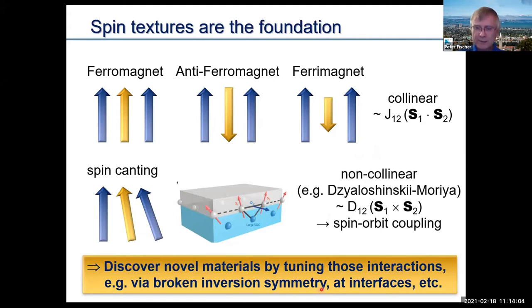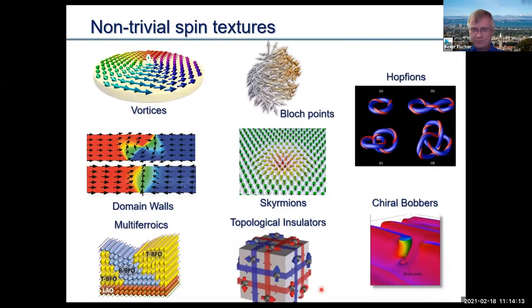And therefore, magnetic multilayers these days keep being very interesting to study, even for these novel spin textures. Now, derived from that, there's a whole zoo of non-trivial spin textures, and I just plotted a few of them here: vortices, domain walls, of course, and then the skyrmions. Skyrmions are a very interesting topic, and I will talk more about them throughout my talk. A very interesting spin configuration where the magnetization actually makes a full rotation when you go through the skyrmion. There are Bloch points that are very interesting to look at. And quite recently, there were also Hopfions, and I will talk about this towards the end of my talk. I will explain a little bit what a spin texture of a Hopfion would look like.